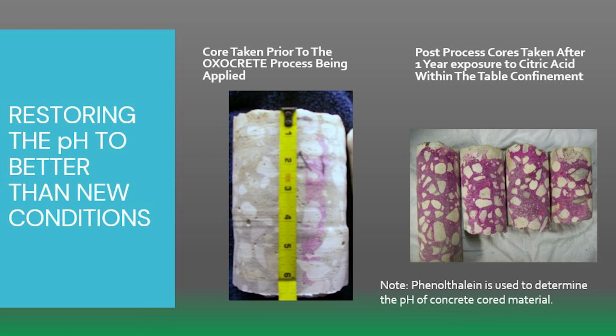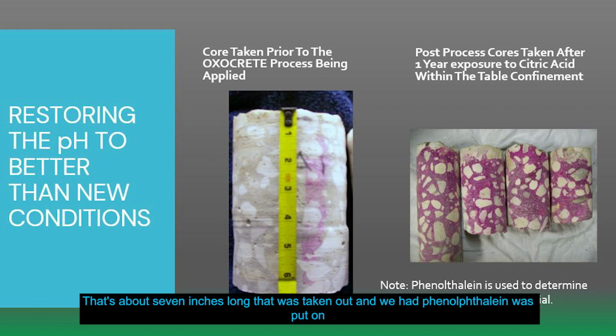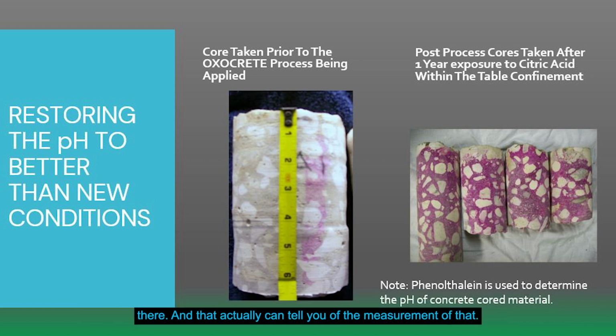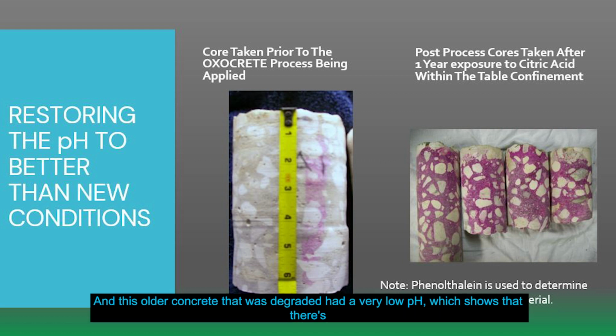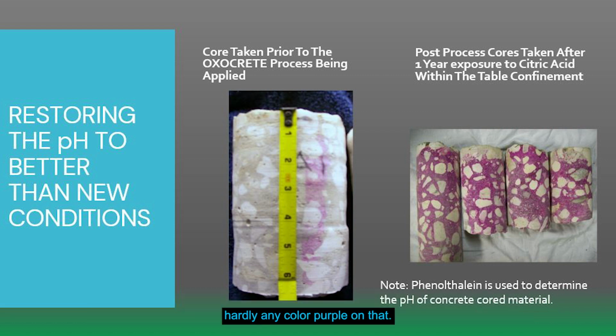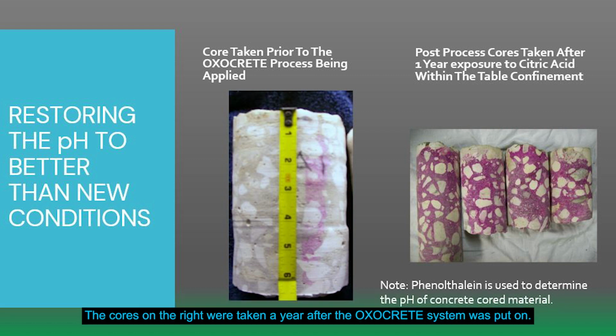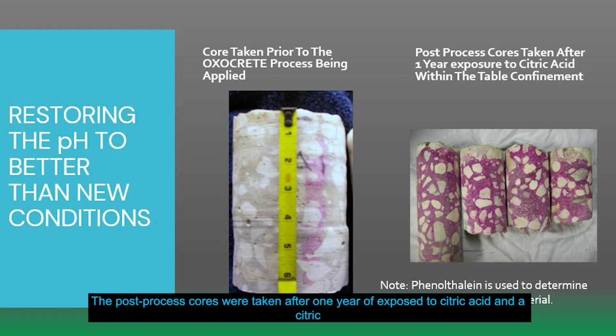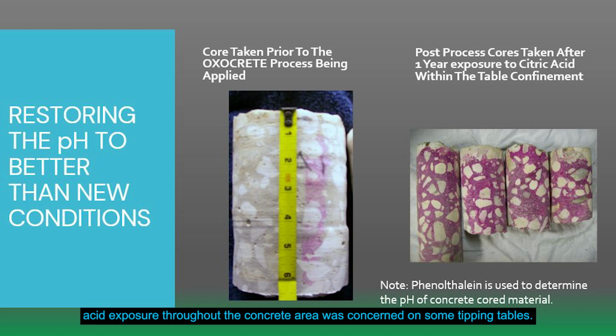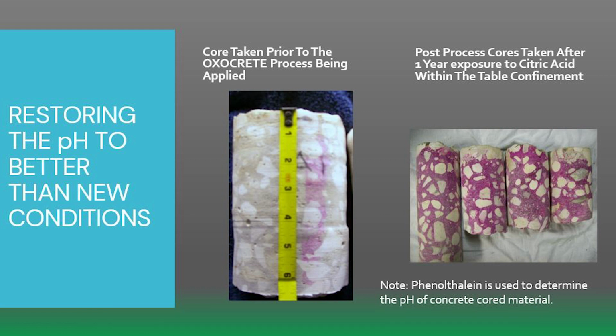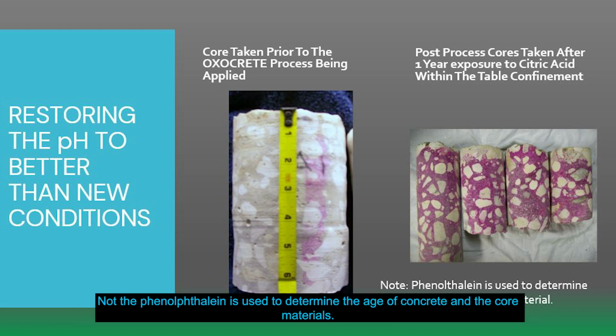We have some restoring the pH to better than new conditions. So we have a core with the tape measure on that's about 7 inches long that was taken out, and phenolphthalein was put on there, and that actually can tell you the pH measurement. This older concrete that was degraded had a very low pH, which shows that there's hardly any color or purple on that. The cores on the right were taken a year after the OXOCRETE system was put on. The post-process cores were taken after 1 year of exposure to citric acid, and the citric acid exposure throughout the concrete area was constant on some tipping tables.